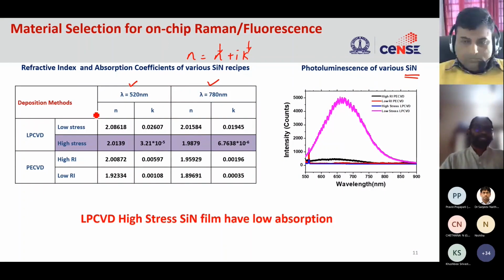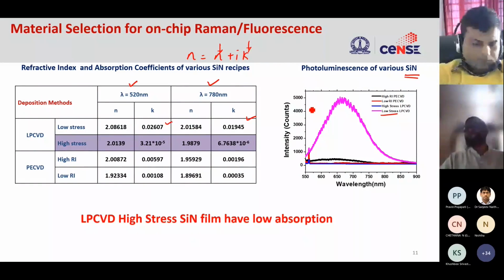So we have measured this N and K. There are various material compositions that we have tried, and we also looked at the photoluminescence. You can clearly see the low stress nitride that we look at, where the K values are very high. You can see here the Ks are very high. So it showed very high photoluminescence, which means there are a lot of states that can emit light.